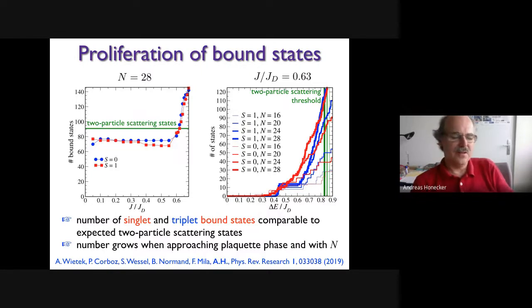And so upon approaching the phase transition and going to bigger systems, you get more and more bound states, and in particular, you get singlet bound states. And we believe that these singlet bound states, which are not being seen by neutrons, since neutrons are blind to the singlet bound states, are the reason behind the unusual thermodynamics.